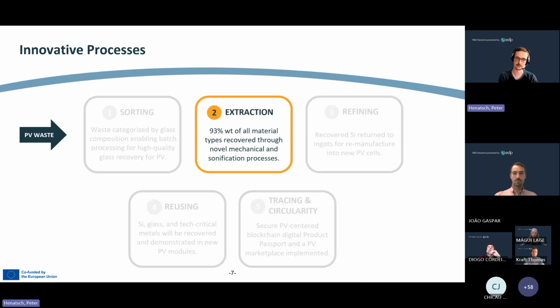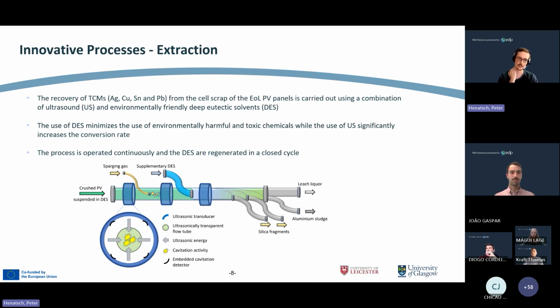For the extraction, we plan to recover 93% of all the material types in the cell fragments. Therefore, our colleagues at Leicester and Glasgow are using a deep eutectic solvent in combination with ultrasound to recover silver, copper, tin, and lead from the cell fragments. And actually, I think within the last meeting, they also presented that there's a full circle which they can run with the deep eutectic solvent. So they could achieve to recover the silver from the solution and reuse the deep eutectic solvent in the same process once again. And so they can minimize the environmentally harmful and toxic chemicals, which are commonly used, like nitric acid or something in this direction, to recover the silver from solar cells.